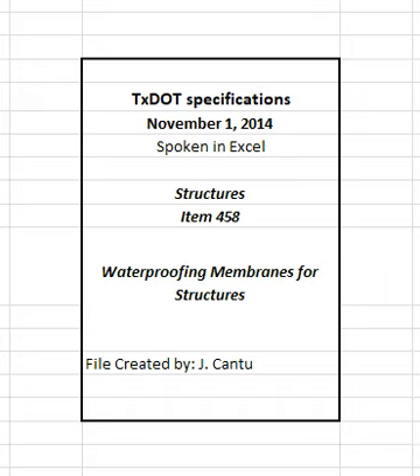Use a minimum coverage rate for each mop coating of 4 gallons per 100 square feet of surface. Apply additional coatings, if imperfections appear, until corrected. Mop the surfaces to be waterproofed in sections at construction joints.